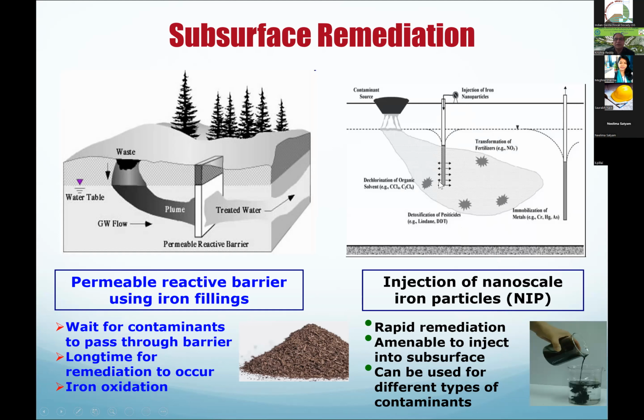Because nanoscale particles form a suspension that can be injected under pressure, under gravity, whatever it is. You inject into the contamination zone, and then the contamination reacts with the nanoiron particles and remediation happens. So you can put not one well, maybe multiple wells to encompass the entire contamination plume, and then the contamination is going to be gone.